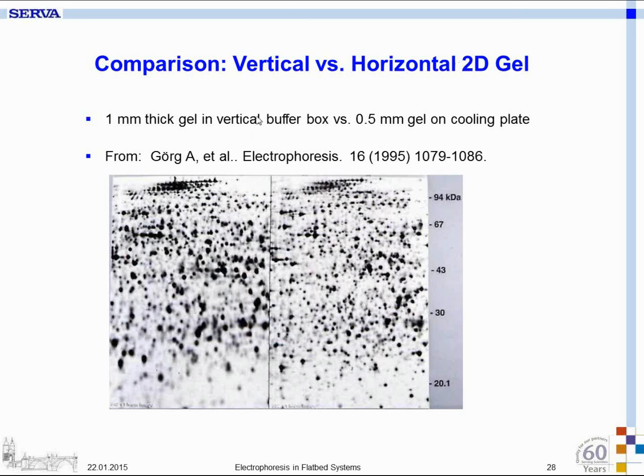And here the result in a vertical gel is compared to a result in a 0.5 millimeter thin gel on a Multiphor cooling plate. This sample was the same, the first dimension was the same, and the staining was the same, silver staining. But you see immediately that with the thinner gel on the horizontal plane, you get much sharper spots and you find more proteins.